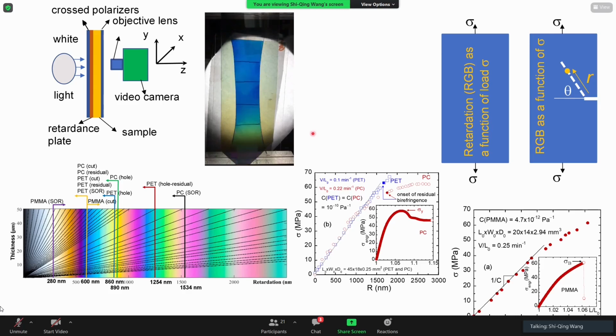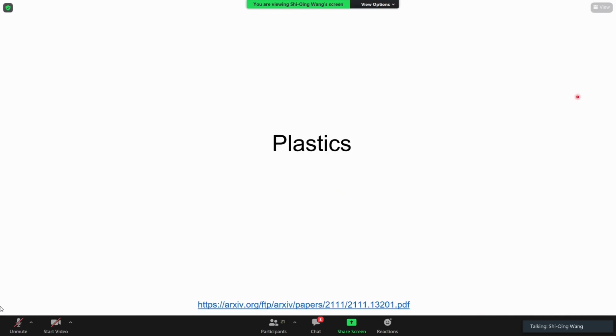And that's what we do. The whole idea was to take an uncut sample, like this movie shows, and build a relationship between the color change, which is birefringence or retardance, and the stress. There's a reliable correlation, as these 2 figures show, largely linear between the 2 quantities, the stress and the retardance. Once you have that calibrated, you can have spatial information about how this birefringence builds up at the tip. Let me give you 2 examples. One is for plastics. We have written a long paper, which has already been released and posted, available to the public.